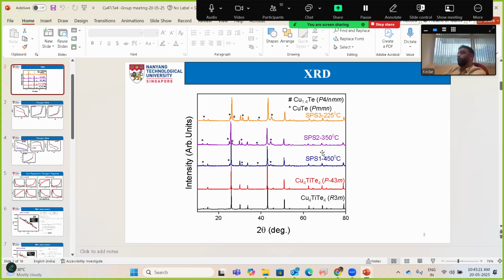That's right. But the point is that if it's stable at 450, then go with 450, then decrease the dwell time. No, just go to 500. More decomposed? Well, apparently not. I don't know. 573 Kelvin is 300 degrees Celsius. You'd expect it to decompose completely, but some magic is happening. Your phase is still there at 450. I would go to maybe 500 under pressure. That is fine.